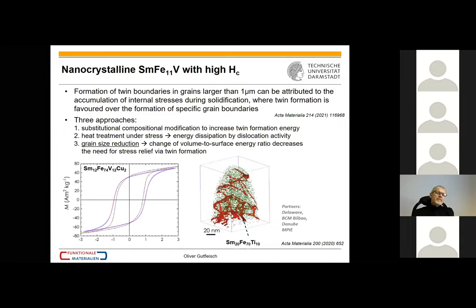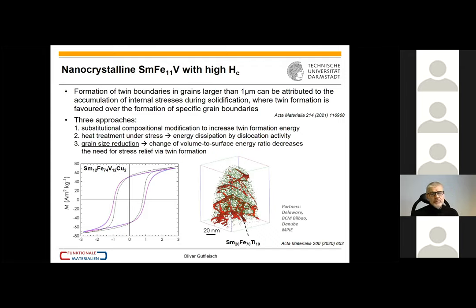So then, of course, you can ask, how can we solve that? And we find that the twin boundary formation is very significant in large grains, larger than 1 micrometer. And then there are different strategies, very briefly here, how to avoid the twin formation. One strategy was pursued here with the partners in Bilbao and Delaware. And you could see that by grain size reduction, we change the volume to surface energy ratio, which decreases the need for stress relief, which is the main driving force for the twin formation. So if you go nano, then we actually can get significant coercivities like it is shown here in the 112 system. Okay.